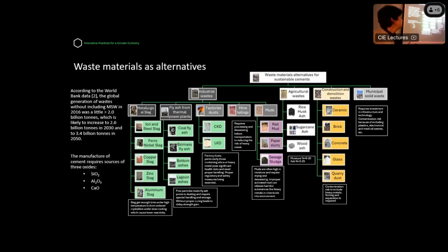And one more thing for lagoon ashes: because of being deposited for a while, they are in contact with water, and mostly the reactive material like calcium, silicon, and aluminum is leached out. So again, the reactivity of the material is reducing, and it also includes a lot of moisture and, based on sedimentation, it aggregates and makes some coarse material, which again we need to grind to make it finer, due to the spec of cement, and use it as cement.